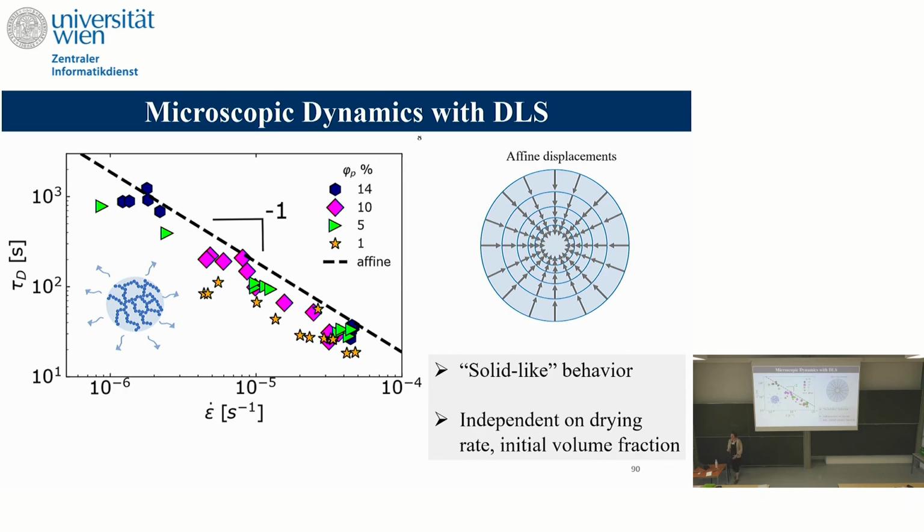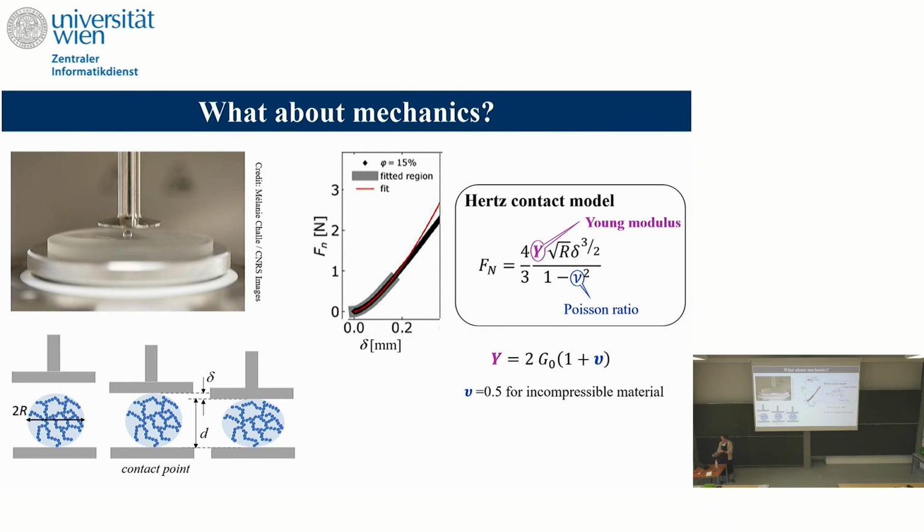It seems quite boring, actually, compared to the shell where we have all this instability. So we say, okay, let's look at the mechanics. So to look at the mechanics, we take a rheometer, we take the bead, and we compress it in the linear regime. So here we plot the normal force as a function of the indentation depth, okay? And you have this Hertz contact model that gives you access to the Young modulus, okay? So we take our gel and we dry it and take it at different drying time and look at what is the Young modulus.